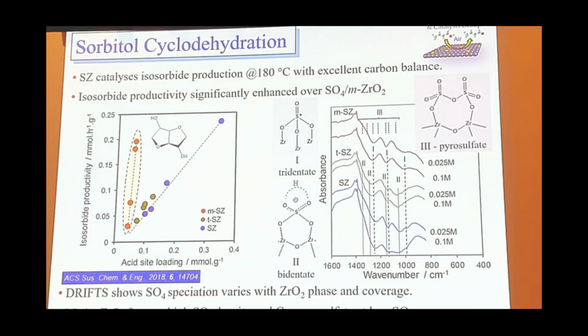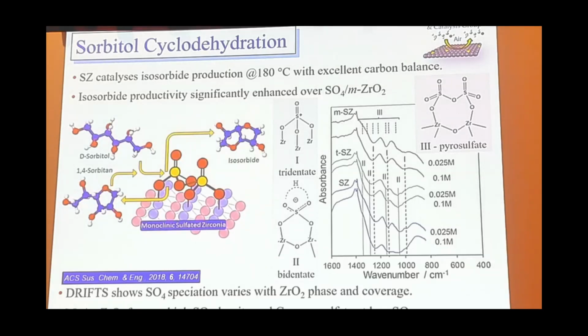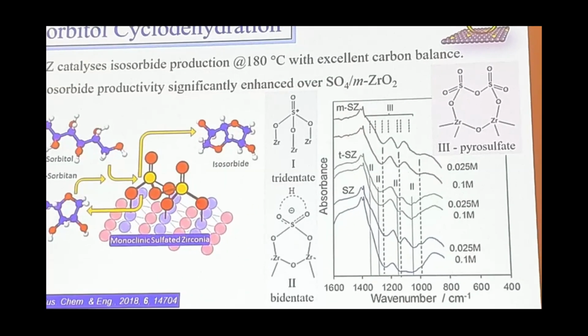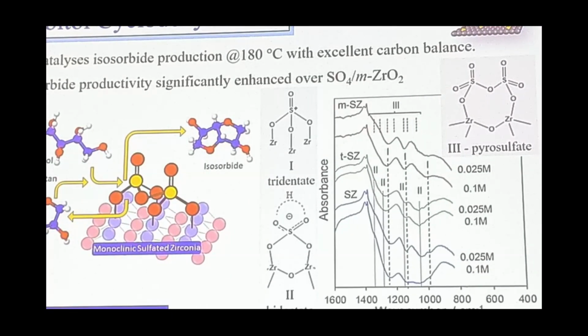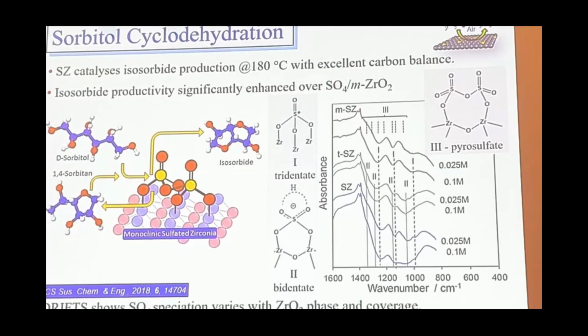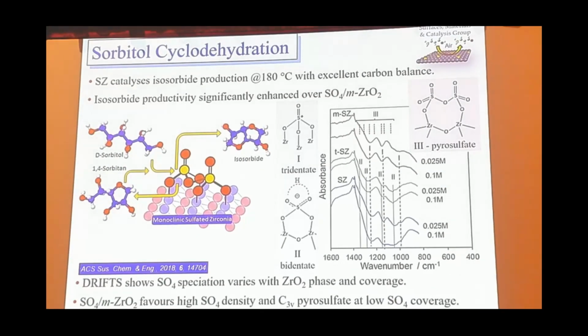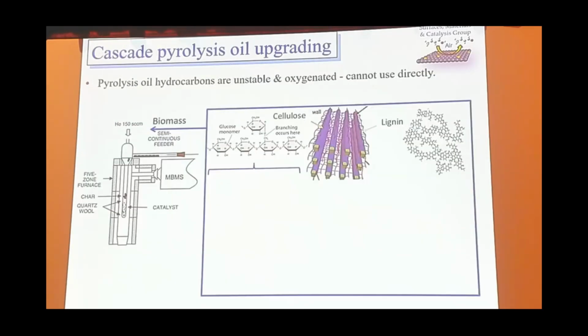But for the monoclinic surface, we have a very well-defined set of bands that seems to suggest what we believe is this pyrosulfate-like species that we think is a much stronger acid. And it's this giving us the high activity for the production of isosorbide through this cyclodehydration step. So the take-home message really is also that the phase of the support matters in terms of controlling those acid site densities and the actual type of acid sites.